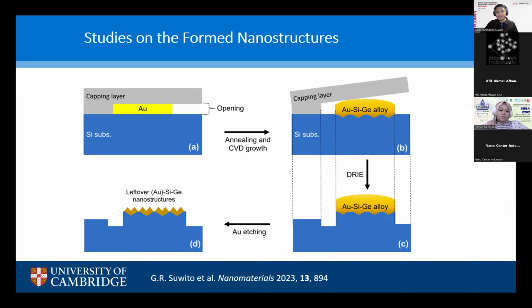This is the schematic of the sample after CVD, in which these are the gold-silicon-germanium alloys, schematically, under the capping layer. And then after DRIE under SF6 for 18 minutes, the sample schematically looks like this. With further chemical etching of the gold, you remove all the gold species, and we hope to leave some silicon germanium nanostructures on the silicon substrate.